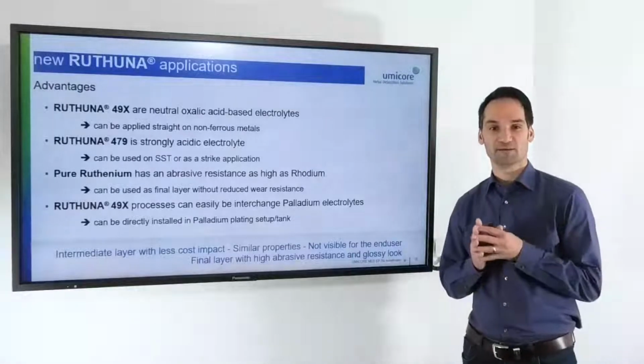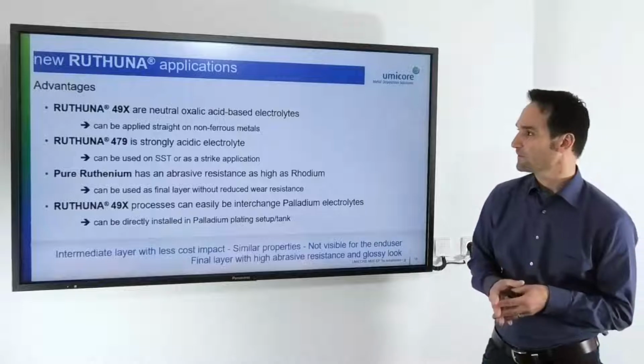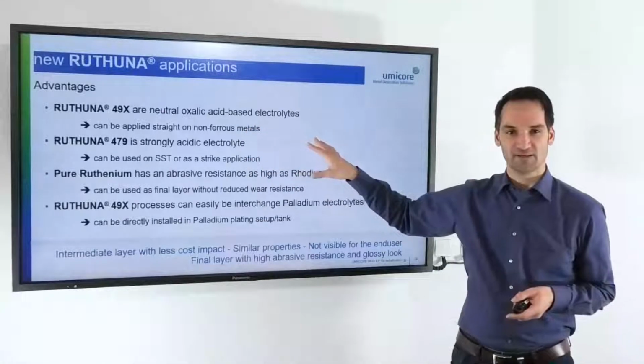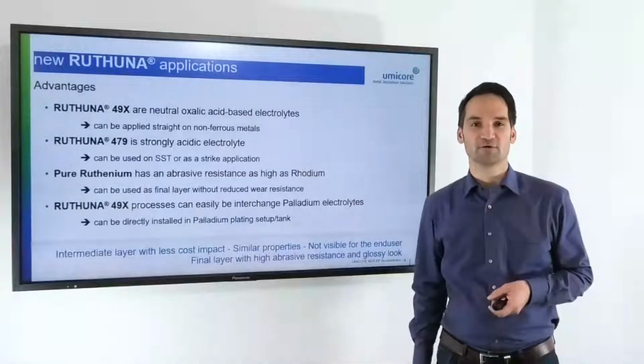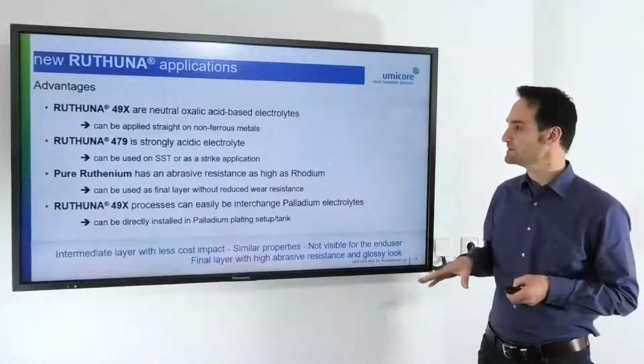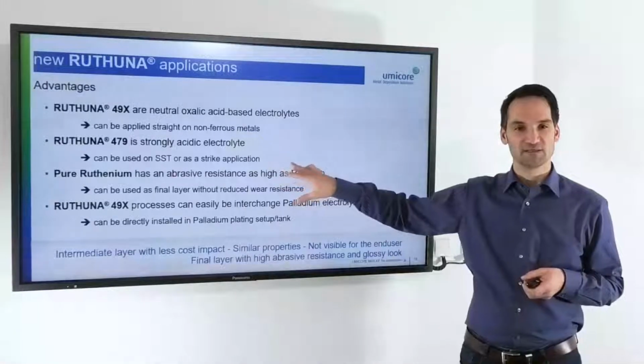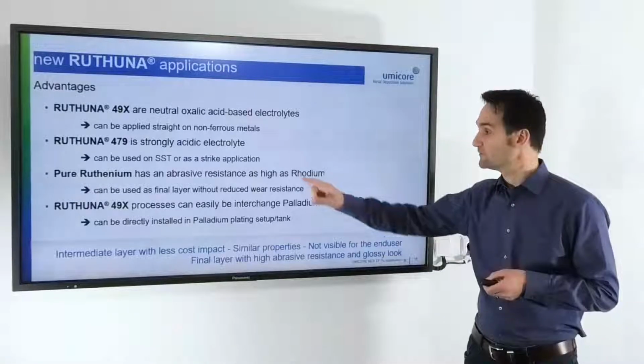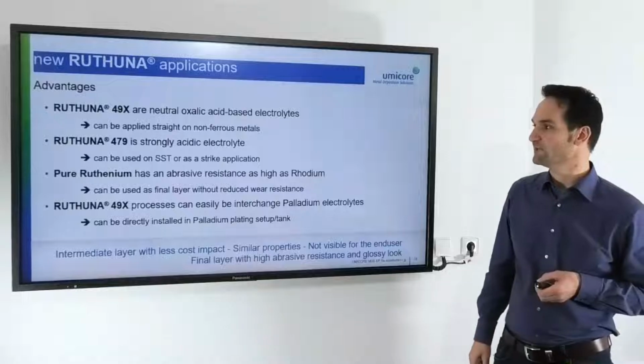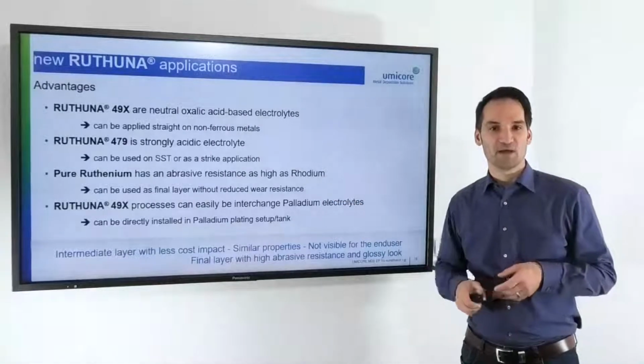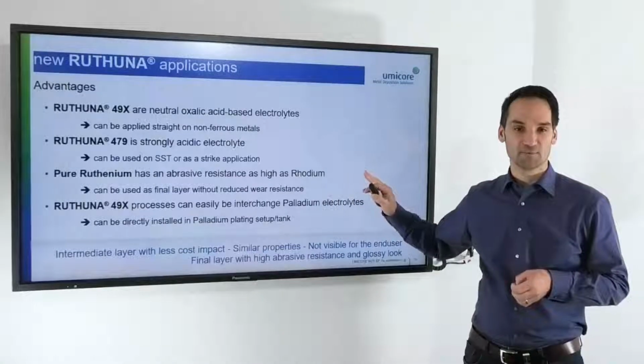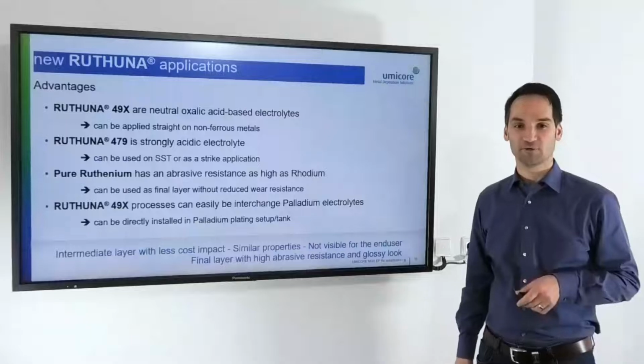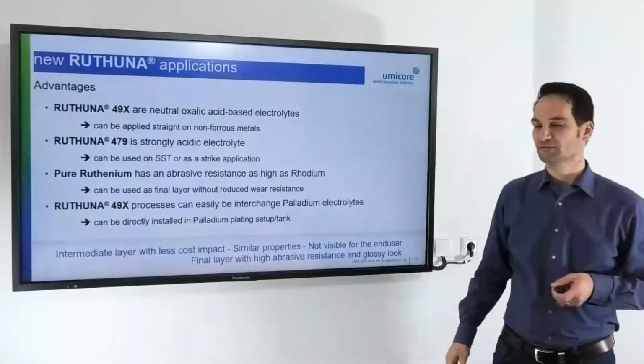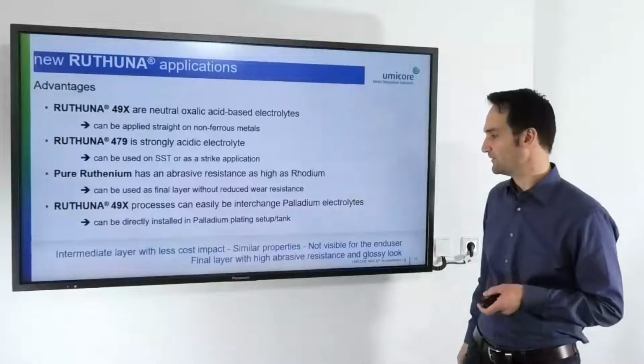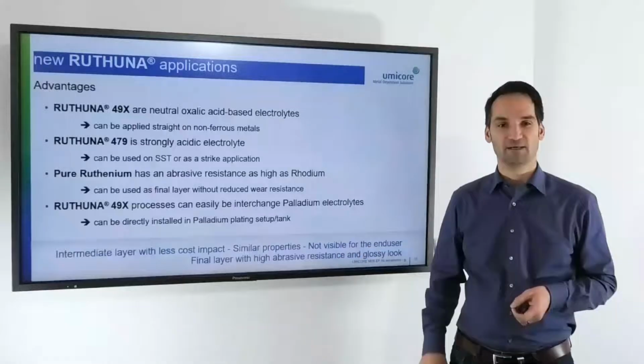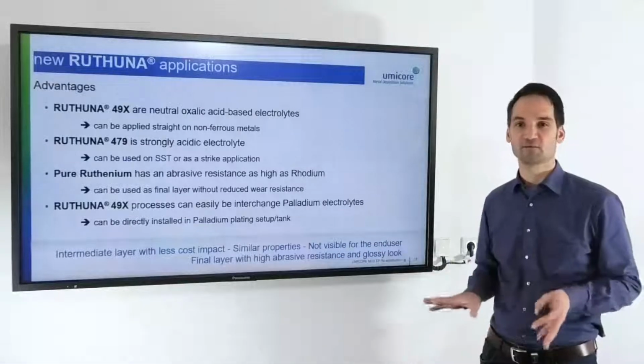Summing up, what are the benefits of the new RUTHUNA? The new RUTHUNA is a neutral oxalic acid-based electrolyte. The advantage is you can apply it directly on non-ferrous surfaces without an intermediate layer. Even if you like an intermediate, even if you like a striking, you still can go for the acidic 479. Pure ruthenium layers have the benefit of a very high abrasive resistance and can even beat rhodium. The new RUTHUNA 49x, no matter if it's the pure one, the nickel alloy or the cobalt alloy, you can directly interchange palladium electrolytes in your production without changing anything in your installations.